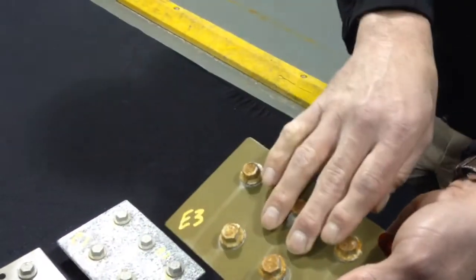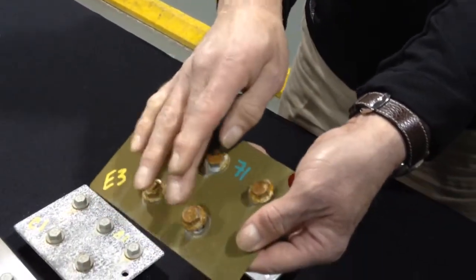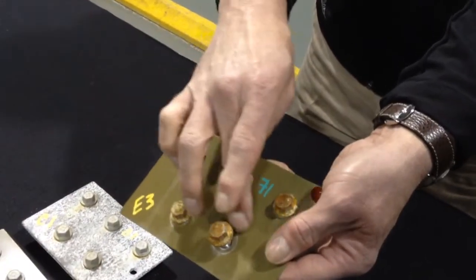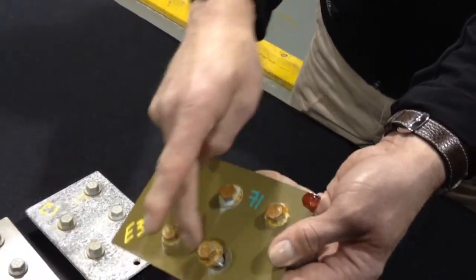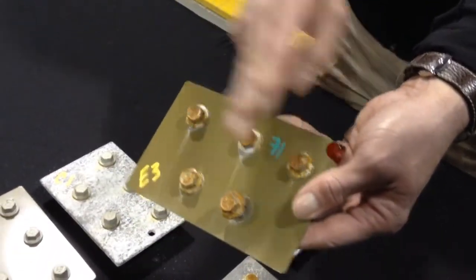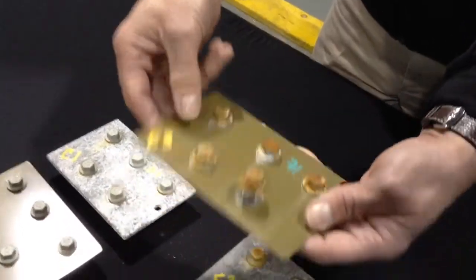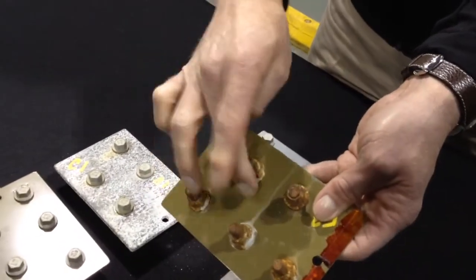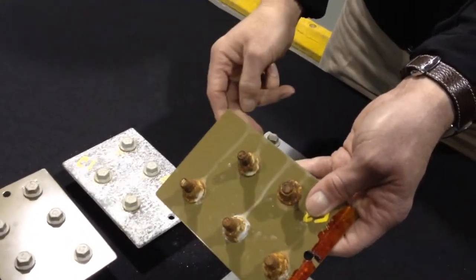In this case, you have bare steel as exposed by the corrosion and bare aluminum, and they've started to corrode. That white ring around there you see is the aluminum corroding. You can see it around the heads of all these fasteners. If you look, you can see it actually really dramatically around this one in particular.